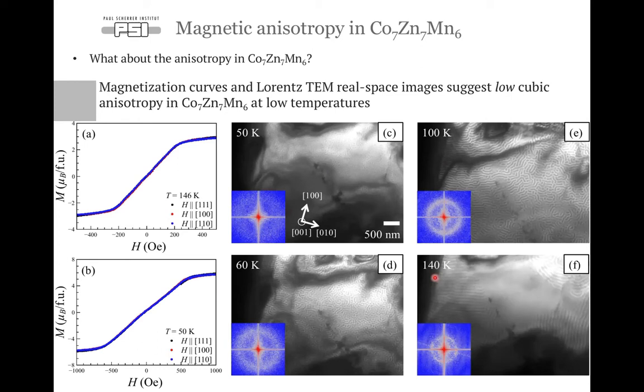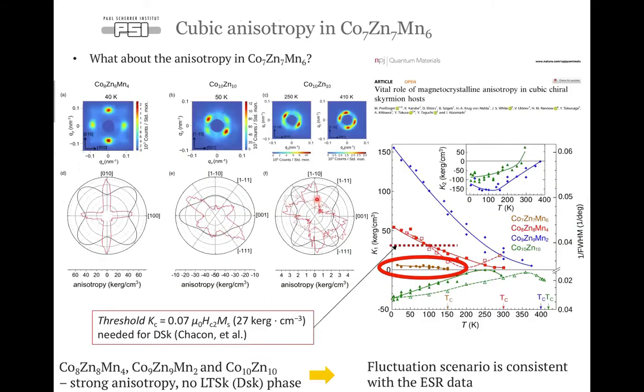That means that the magnetic disorder is much stronger than the magnetic anisotropy at low temperatures, also suggesting that the magnetocrystalline anisotropy in this material at low temperatures is quite small compared to the copper selenide case discussed in previous works.